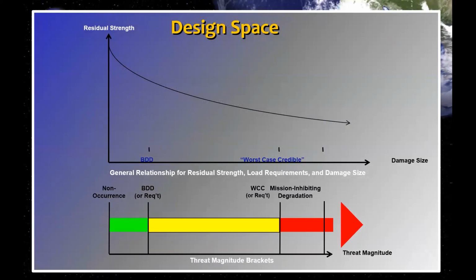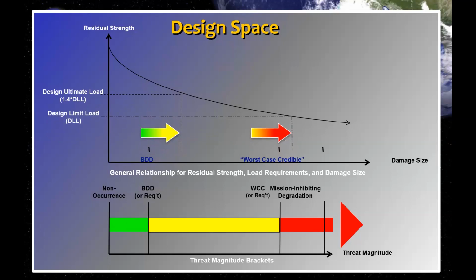Okay, so this will be my last chart to kind of talk about. If I think about the design space, that curve I just showed you, residual strength versus, say, damage size, we've got this idea that we want to design to, to understand what that means relative to NDE, and the other is relative to what's the worst case credible defect that we could put into our structure. And we need to certify our design so that we can tolerate that kind of damage in our structure and write margins against that. And so our typical design ultimate load requirement of 1.4 times design limit load needs to be to the right of this. And from a worst case credible damage standpoint, what's the worst thing that could happen that we think could occur to the component, we need to show that we can at least tolerate that to a safety factor of 1.0.